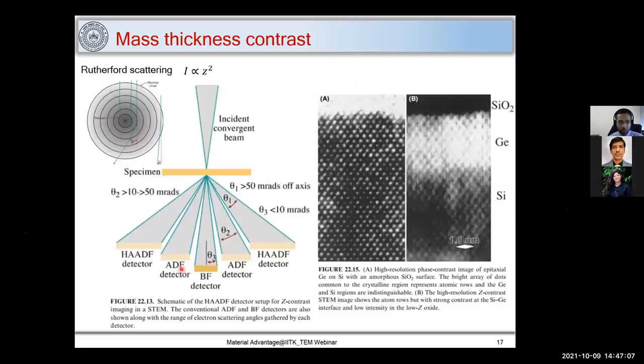Now here I would like to give an introduction to the HAADF or ADF detector and the bright field detector. So we have a specimen here and we converge a beam in a way where it forms a very small spot on the sample, and when it interacts, it creates a signal. It creates a signal in a forward way, and that is detected by this bright field detector. We'll be looking at bright field and dark field as we go along. So it is actually on-axis detection. That is why it is called bright field.